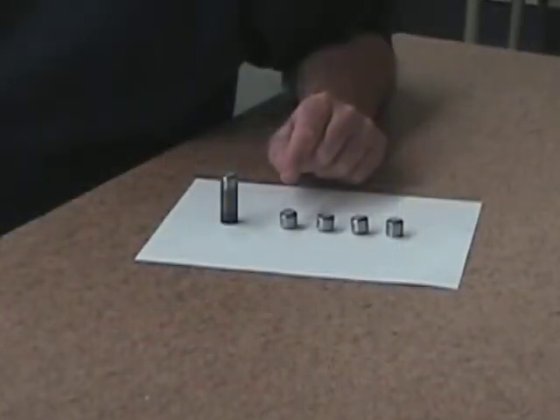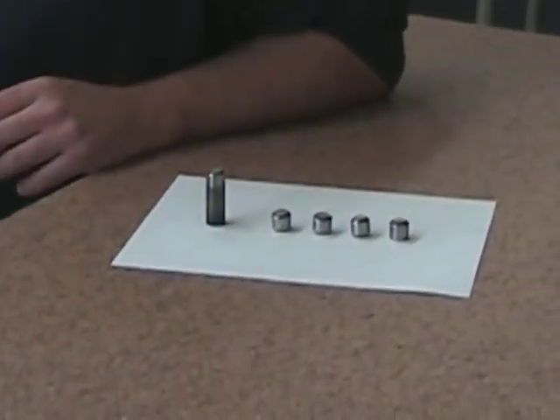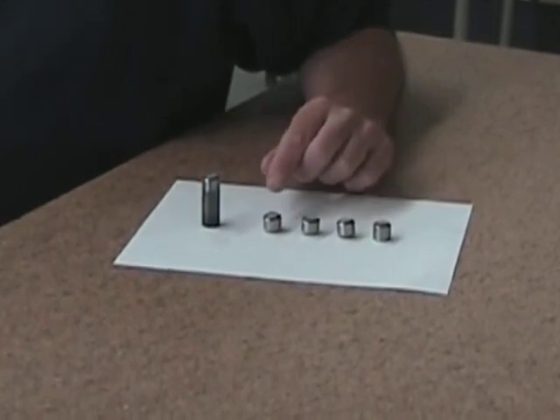But we did that before even breaking the sections apart by using a file to compare hardness. The fourth piece was the first one that was a little less hard, and the shank wasn't hard at all. So pieces 1, 2, and 3 were clearly in the critical temperature range for hardening steel. The next thing we noticed was that section 1 and 2 were very easy to break off, section 1 even easier than section 2. But section 3 became quite difficult to break, and section 4 was almost impossible to break off.